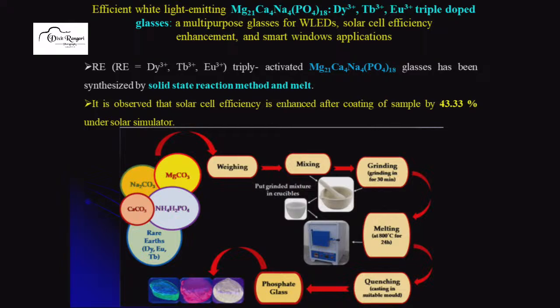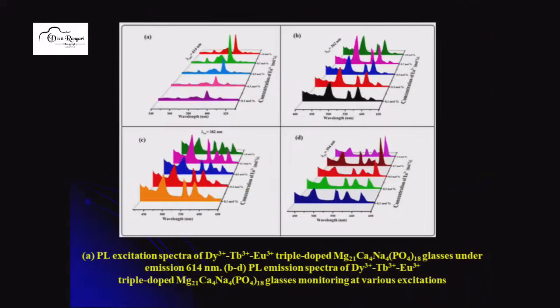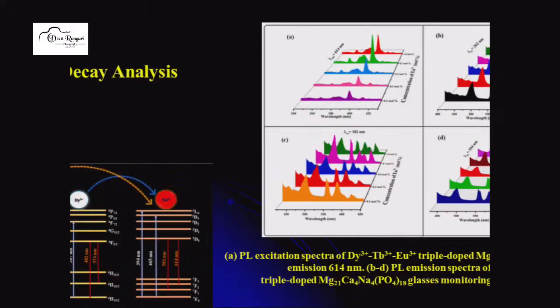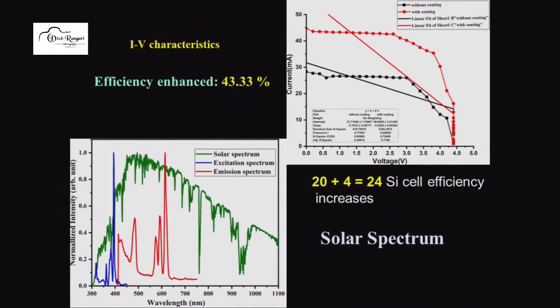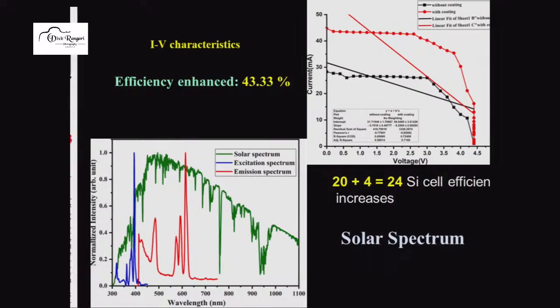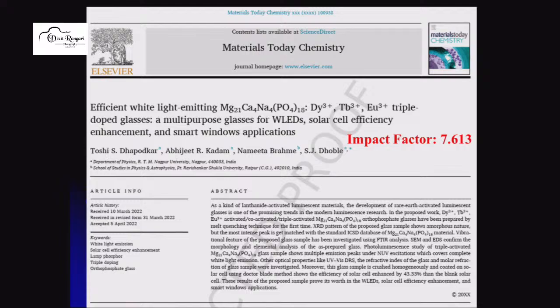Now the next material, this is magnesium calcium sodium phosphate, Mg21Ca4Na4(PO4)18, triple doped with Dy, Tb and Eu3+, prepared by the mentioned technique, solid state reaction method. And you can see the efficiency increased by 43.33%. It is very good. So 20 plus 4 is 24%. Silicon cell efficiency enhancement. So this is a very interesting material, and the paper is also published, 7.613.